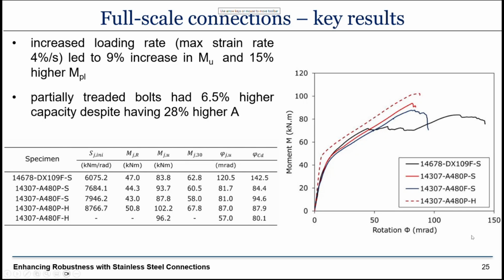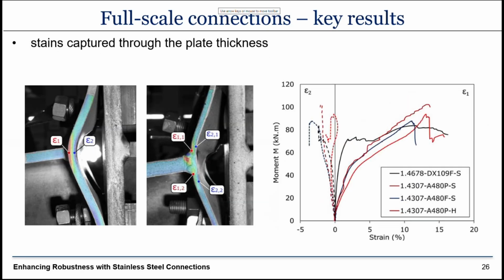The partially threaded bolts had 6.5% higher capacity, despite having 28% higher cross-sectional area. And that is because of the thread-forming process causing enhanced material properties in the vicinity of the threads. The same conclusions were verified by strain measurements, where we can see that at high strain rates, for the same strain, we got higher moments, because for the same strain, we got higher stress in the material.